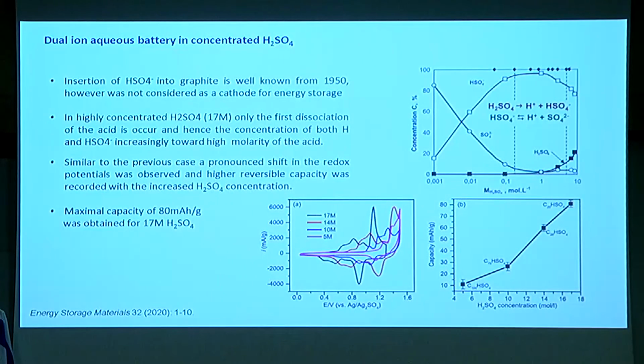Now I want to speak about a non-lithium system. This is another interesting system. Here we're speaking about concentrated sulfuric acid. It's been well known for many years that bisulfate can be inserted into graphite. But still, no one considered it as an option for energy storage. And what we did here, we tried to increase the concentration of the bisulfate, because we know that at high concentration only the first dissociation of the sulfuric acid occurs, and hence we're increasing the concentration of the active species, the bisulfate, but at the same time we reduce the concentration of the water.